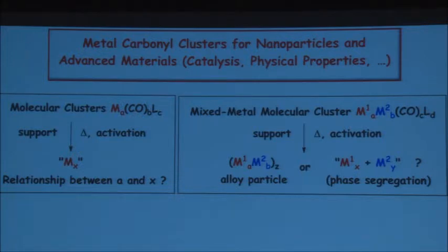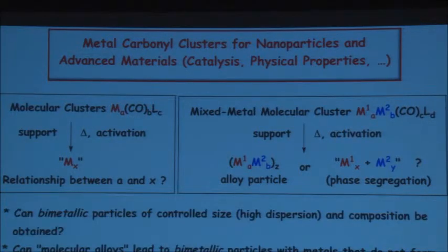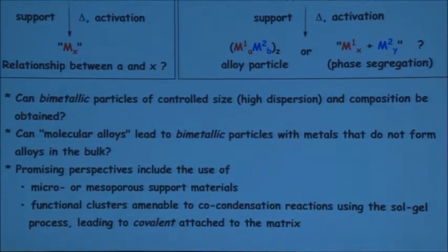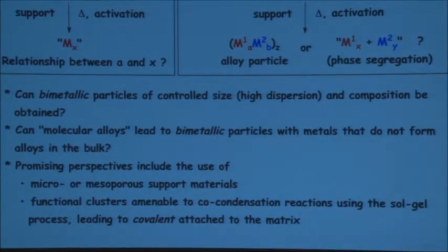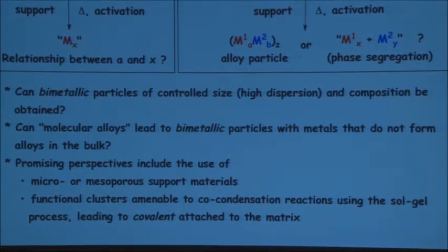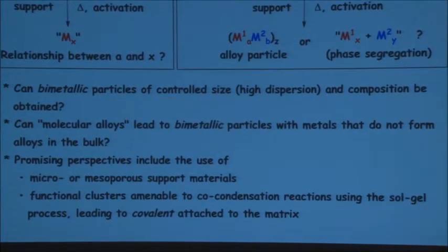If we can keep the alloy throughout, this would be a very nice, soft way, with very mild conditions, to generate metal particles that one cannot necessarily generate from conventional methods. So that could open a number of perspectives. So the idea was, of course, can that be made? Can we obtain bimetallic particles? Can these molecular alloys, I quote that here because this is not a proper alloy, but you understand the message. The two metals are in close proximity in these nanotype particles because they have nano size.